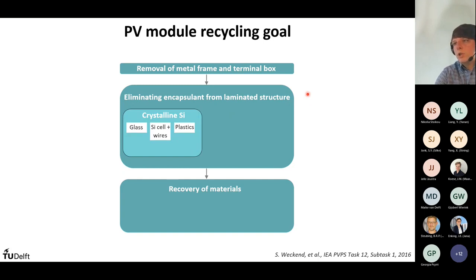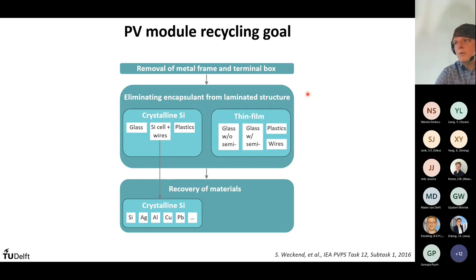And we have to differentiate. 95% is crystalline silicon, and for these we have a different valuable material than for thin film silicon, which has a market share of about 5%. And there we get a different bill of materials which can be recovered. And there is no law or regulation on which materials can go into a PV module. So in theory, anything can be in there. So that's also a challenge when you get a PV module. It's unclear what exactly you have in there. You have some general experiences, but it depends on the manufacturer and then on the year. And it keeps on changing, so you will need to adapt your processes from year to year with the modules that come in.